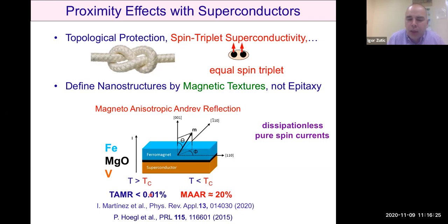Here, it's just a tiny part of 1%. What is remarkable is that once this structure is cooled below the superconducting temperature, rotation of magnetization gives orders of magnitude larger magnetic anisotropy. So this was our theoretical prediction 5 years ago, and now it has been confirmed experimentally. In other words, if one goes to the superconducting state, yes, it will be possible to have spin triplet superconductivity, but in addition to that, it may be possible to amplify small effects of spin-orbit coupling. So the superconducting state may become very, very sensitive to otherwise negligible contributions to anisotropy.